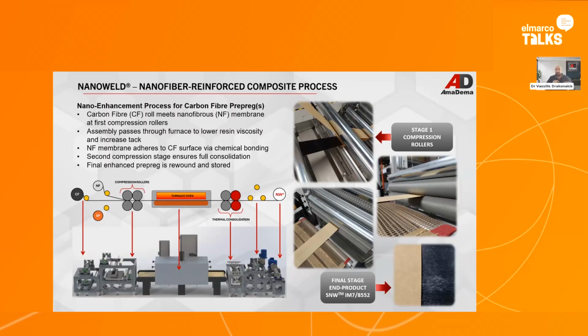or other technical fabrics, before they get wet with the resin, they do have a sizing around the fiber. So when we do the NanoWeld on a dry form, the nanofiber adheres to this sizing, making the load transfer mechanism that I described before much more efficient. So eventually we have better properties. But if we want to use an off-the-shelf prepreg system, this connection with the sizing is not there. However, we still have an increase in the final properties.